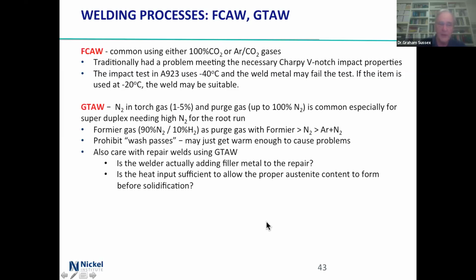You can use Formier gas. The hydrogen will take out any heat tint if you've got a bit of oxygen around. Formier gas to nitrogen to argon plus nitrogen. Largely, people are going to use all nitrogen. You really don't go doing wash passes, because you're just going to get the thing warm enough, probably to cause problems, without actually doing much in there.